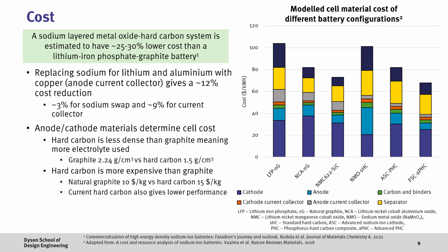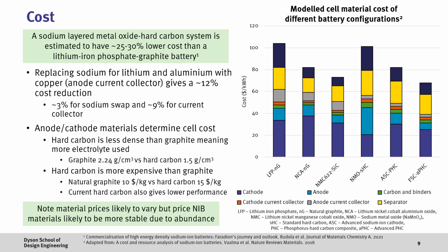If we then compare the costs of different lithium-ion and sodium-ion battery configurations, we can see that there are potential cost advantages, but the exact number depends heavily on the chemistry being used. Here, we compare three popular lithium-ion battery chemistries, LFP, NCA, and NMC, with different sodium-ion battery configurations. Here, in the near term, this is likely to be a battery with a sodium layered metal oxide cathode with a hard carbon anode, but in the future, the cathode may well improve, with some viewing future anodes as having a blend of phosphorus which has a higher specific capacity. However, when interpreting these numbers, it's important to note that material prices do vary and there's uncertainty around future material performance.